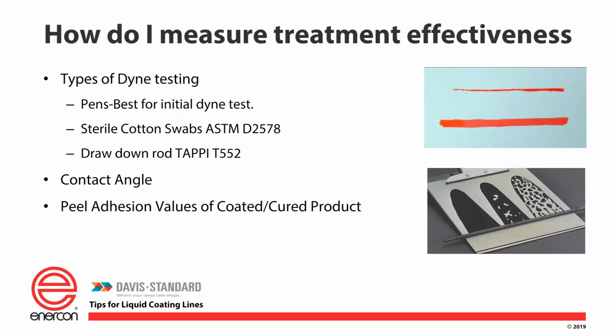Now, the next way we can do this to measure the effectiveness of treatment is a contact angle, and there's many different versions of those out there. They've been around for a long time. And basically what you're doing is you're taking a measured drop of a liquid, usually deionized water or some such liquid, and you apply it precisely to a very small sample of the treated sheet. And the droplet is applied, and you're looking at the contact angle of that droplet on that surface. So really, they're measuring how much that droplet spread, and then measuring the angle of that.